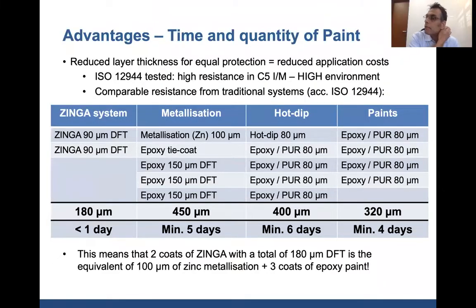And one big advantage is the speed, because since we are applying less coating, that means we are applying only 180 microns in a scenario where normally my paint thickness with epoxy would be 320 micron. I'm applying only 180 microns. So the amount of coat needed or amount of Zinga needed is far less. And the time needed to apply is within a day itself. You can do it what normally would take 4 days due to high drying time. Humidity helps Zinga because the zinganization process takes place faster.